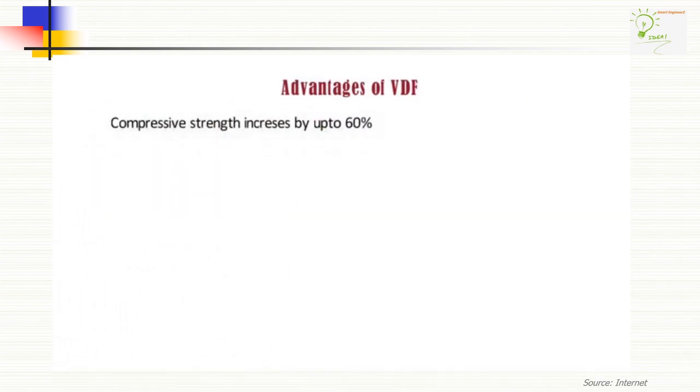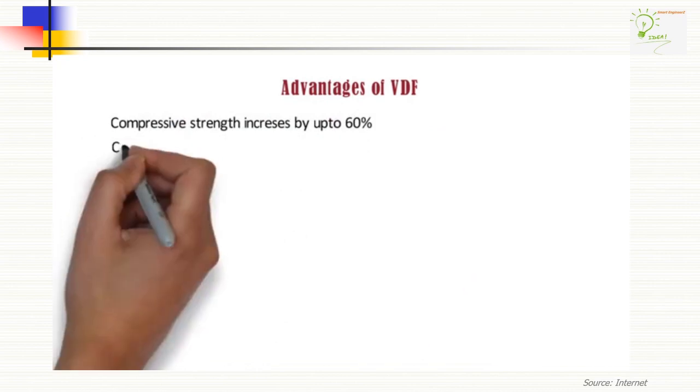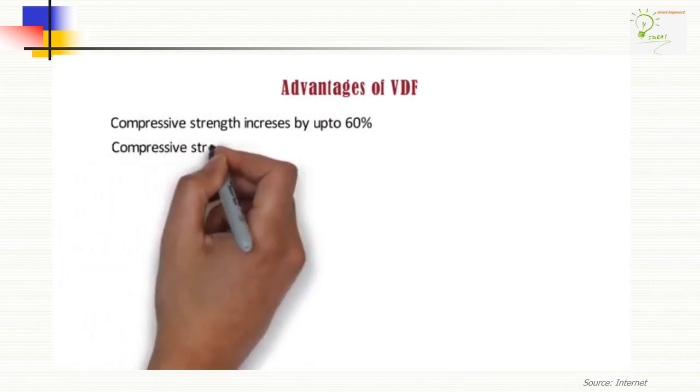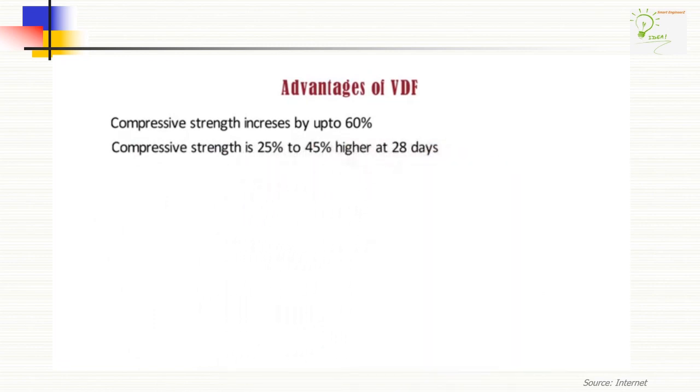Advantages of VDF. The compressive strength of VDF concrete increases by up to 60%. The compressive strength of VDF concrete is 25% to 45% higher at 28 days as compared to normal concrete.